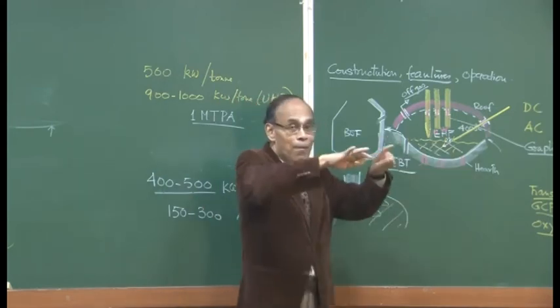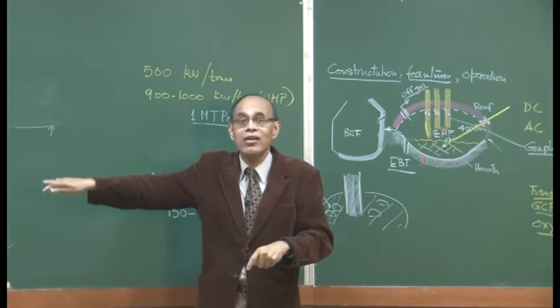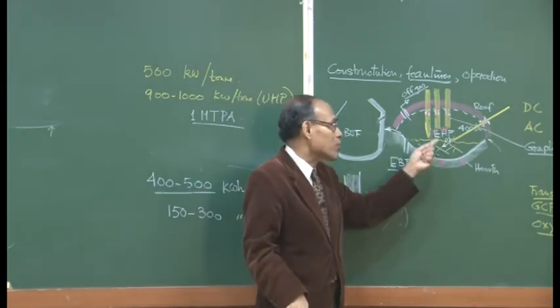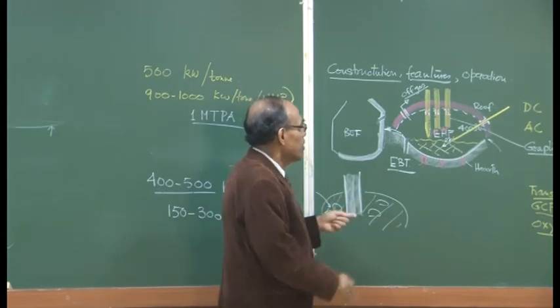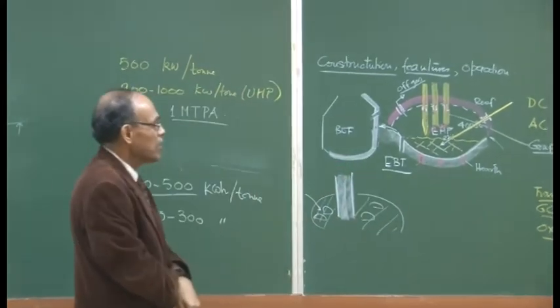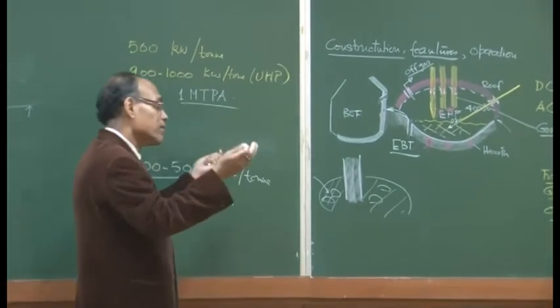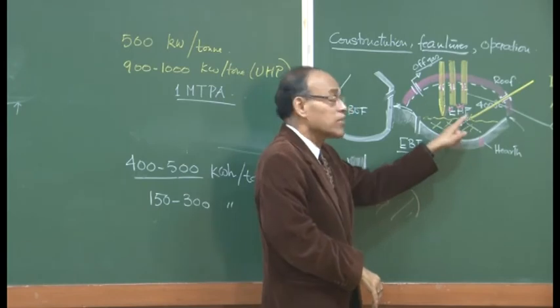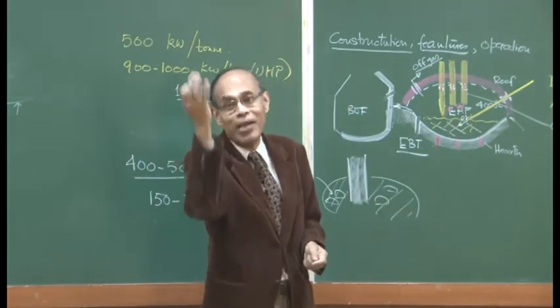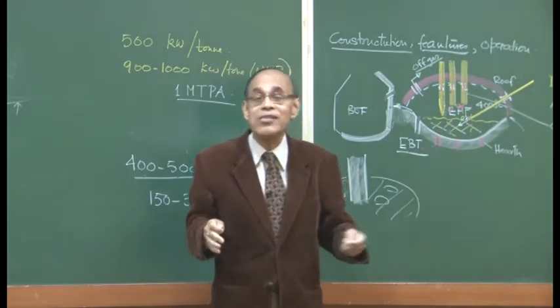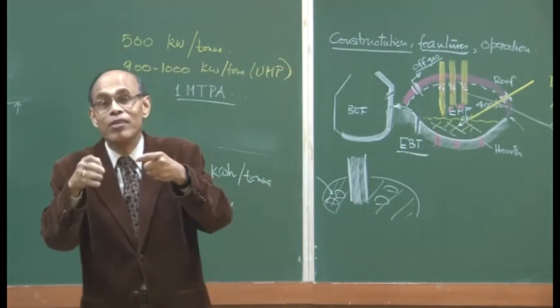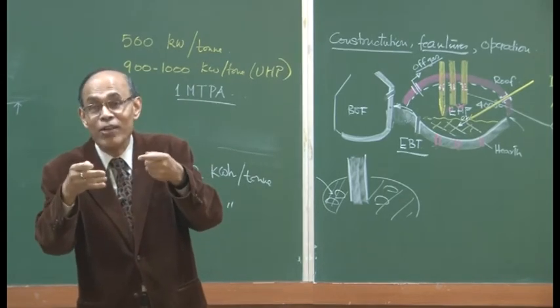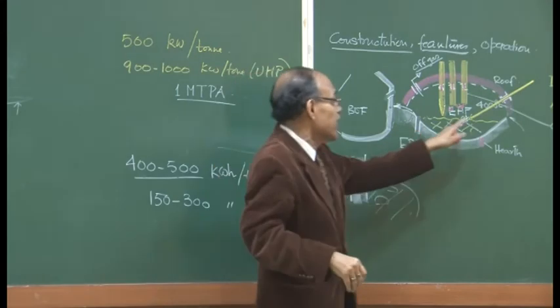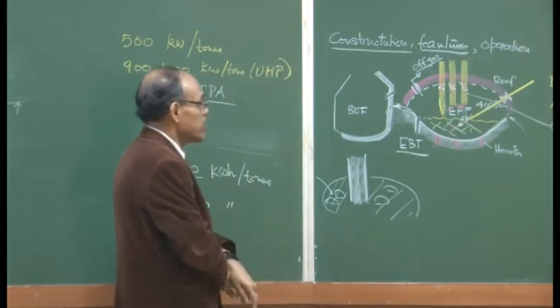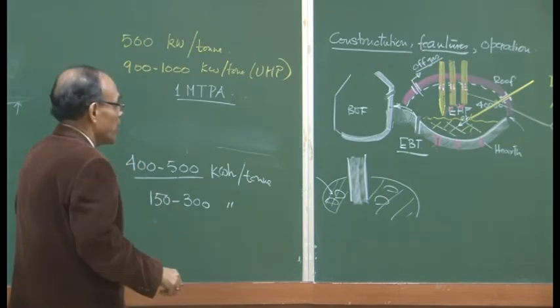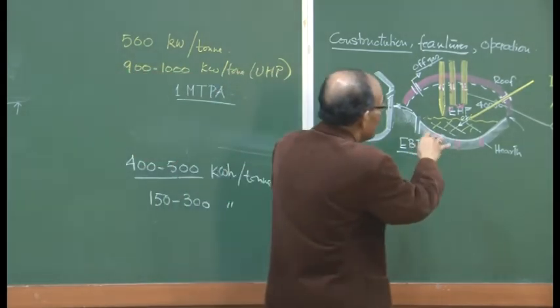The entire upper part of the furnace is available the moment you have moved the roof away along with the electrodes, and from the top you can charge the material. And if you are charging hot metal, that hot metal can be charged from the side itself, and then the roof can be brought back and blowing of oxygen can be started. Oxygen, if you start right from the beginning, that can expedite the melting rate also, because in the presence of high temperature and oxygen, some scrap will try to become iron oxide, generating heat also. So, the oxygen lancing can also expedite the heating rate in the furnace itself in presence of electricity and a high temperature. Okay? And then you can make the steel and then you tap it.